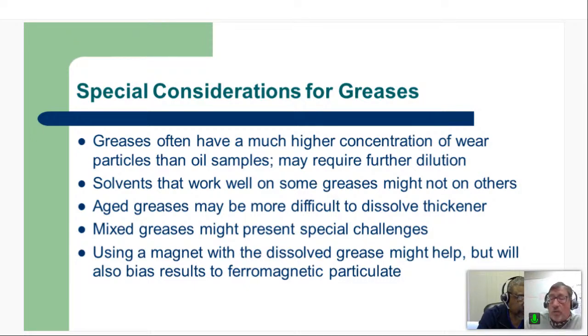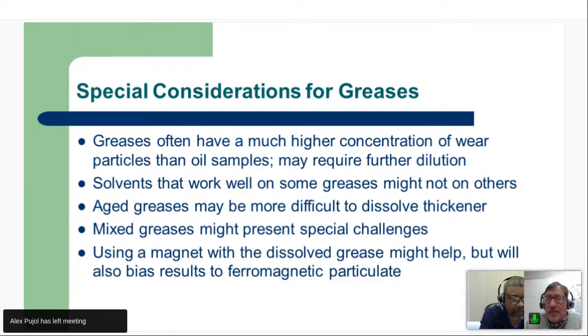And I said that aged greases or stressed greases may be more difficult to dissolve than a grease that hasn't undergone those same kinds of changes, sometimes oxidative type changes. Then you might have mixed greases, and we find this a lot of times, where two different products ended up in the same bearing housing, and now here comes that sample, and how do you dissolve the mixture? Maybe one solvent would work well on one and not the other. So again, another challenge. One of the things that we've been doing is almost a secondary ferrous step, and that is to use a magnet when you first dissolve the grease.